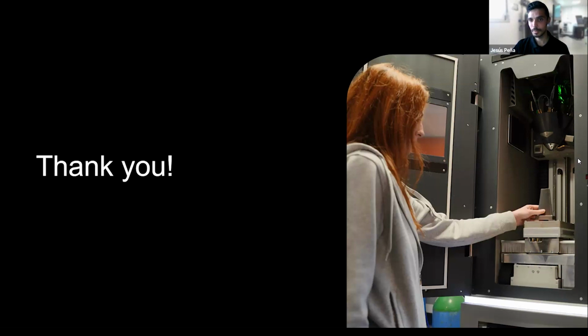Are there any parts made by this 3D printer used for biomedical implants? We made several tests. We made tests in titanium already, and at least for Spanish laws, we needed to get an oxygen content of 0.11%. This is what we got with our system with the titanium grade 23. That is the one that we were in need for some applications.